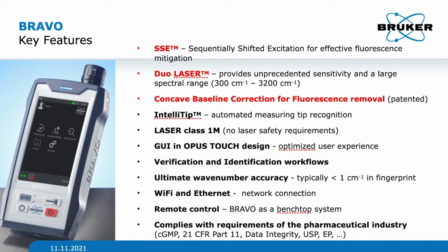Very, very useful. We also actively control both lasers so that we can actually shift a few times around, moving the laser wavelength, emission wavelength around just a little bit, and then divide off the fluorescence, which doesn't really change with such small shifts. And lastly, in addition to the previously mentioned SSE that is patented, we also have the patented concave baseline correction for fluorescence removal. This uses concave or parabolic type functions to strip off fluorescence or scattering, again, which is most useful.